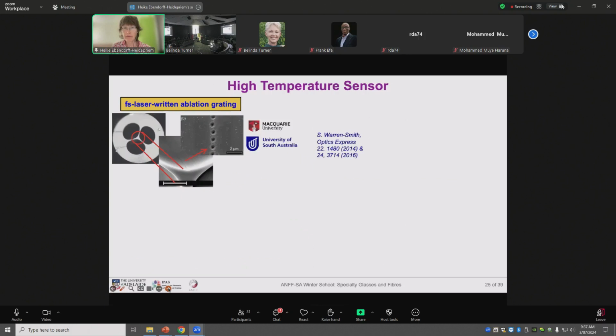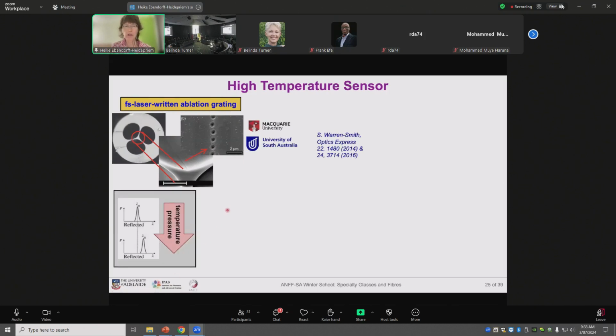I want to give one application example where the holes are not filled with any material, but the holes are used to make a fiber where the light is guided in this core. So it's a single material fiber, pure silica. Taking the femtosecond laser, a so-called grating is written into the surface of the fiber core. And again, because the grating is written via air holes, this is also a single material grating. And what it allows us then is to go to higher temperature.